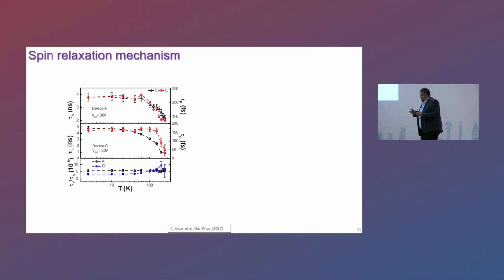So we managed to succeed in inducing spin into this non-magnetic material, and it can diffuse over 6 micron. But after 6 micron of length, the spins are dying, right? So we need to understand what's happening so that we can create new strategies to improve further. To understand, we compared the spin relaxation times with the momentum relaxation times. These are spin transport measurements and also 4-terminal charge transport measurements, and we directly compare their dependency on the temperature. As you can see, both of them are scaling quite similarly with the temperature.